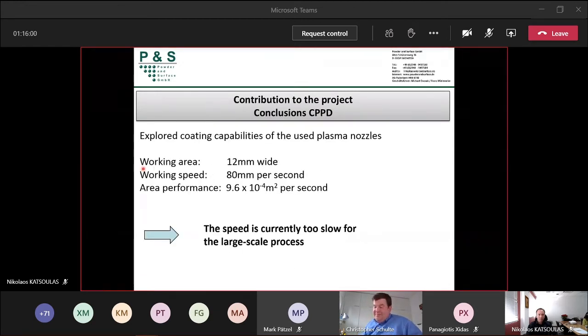Yeah, this is another big point. It turned out that the capability of the coating with the used plasma nozzle is not fast enough for the large scale process with Thrace. You can see here some parameters we already use for the coating of our samples. We have a stripe of 12 millimeters wide and the speed is 80 millimeters per second. So it's not so much area we can coat per second. That means we would need to use a lot of nozzles to bring an inline coating into Thrace, and at the moment this is not really an option because the investment cost for this would be too high.